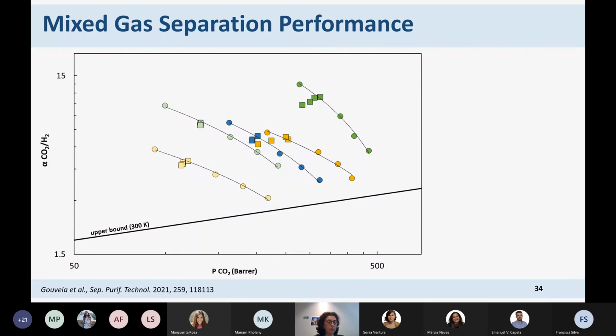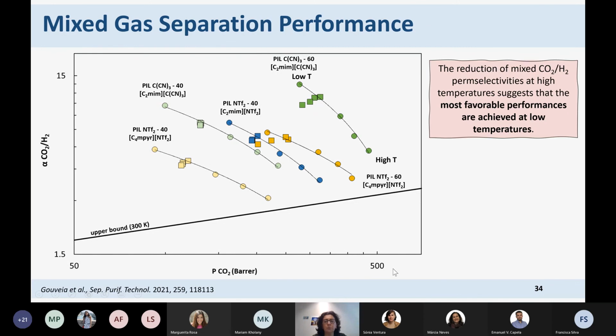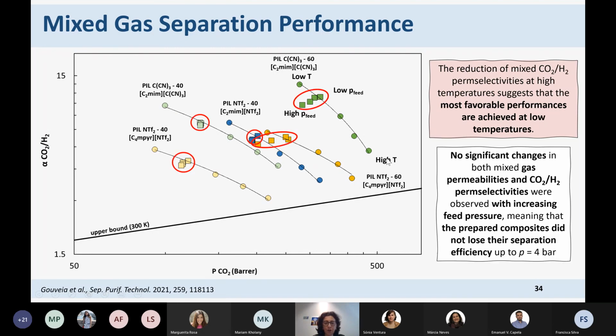So if now we talk about the Robeson plot, where we evaluate how good we are doing, these are the results. In terms of the separation efficiency, in terms of the permeability of CO2, which is the most permeable gas. In terms of temperature, we see a reduction when we go from the low temperature to the high temperature. And in terms of pressure, we can see that we also have a reduction, but a little reduction compared to that of temperature when we use different feed pressures.